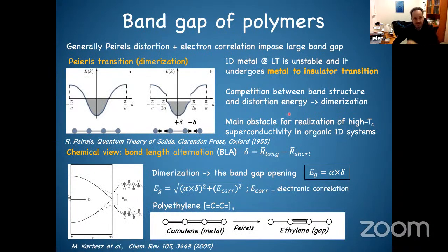That is what we condensed matter physicists know as the Peierls or dimerization case, which comes again from what I told you about screening in one-dimensional systems: a metallic system, one half filled, is always unstable. That's what Peierls showed. And there is a transition from metal to insulator. So you open the band gap, and the gain in electronic structure is always much higher than the deformation energy, when you make one bond shorter and one bond longer. That's basically the Peierls effect, and it can be generalized to what we call pseudo-Jahn-Teller effects.